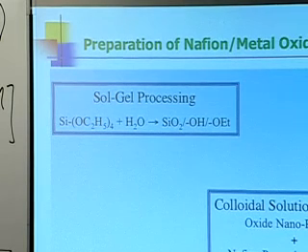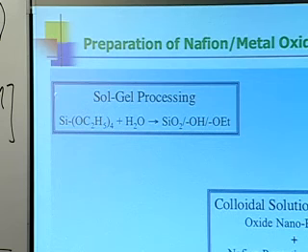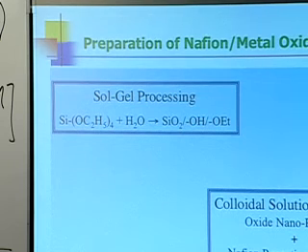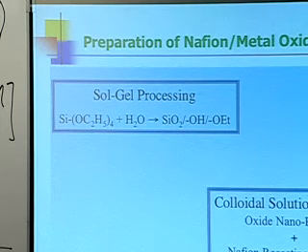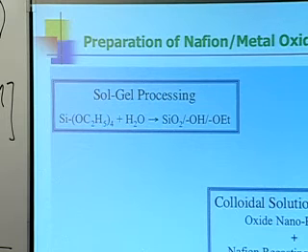Something that we found, because this does involve some chemistry, is that you could get a very similar result by just taking small particles, nanoparticles, if you will, of your favorite metal oxide and mixing them in to the Nafion. That is, take the Nafion, solubilize it, get it in an alcohol solvent, throw in your particles, stir everything up, sonicate a little bit to get a really nice distribution of things, and recast your membrane.